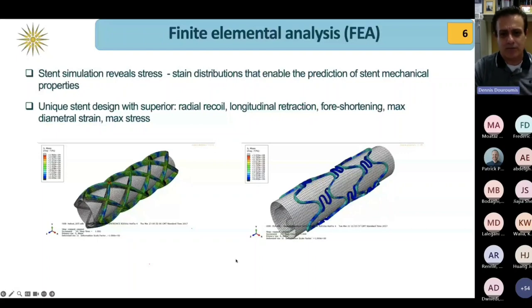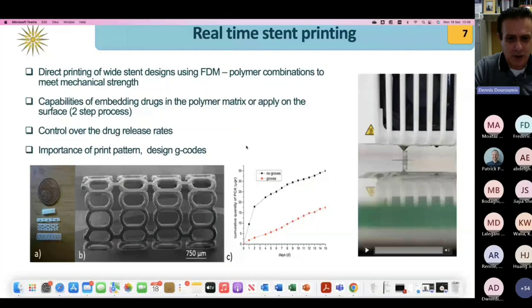So what we did then, we moved to 3D printing of these different designs by using FDM. And as I mentioned before, the capability was to print plain designs and apply the drug on the surface by using another technology which is called inkjet printing. And in that case, we could control the drug release profile. So we know that it's different. The release rates are different when the drug is coated on the surface or when it's embedded within the stent matrix.